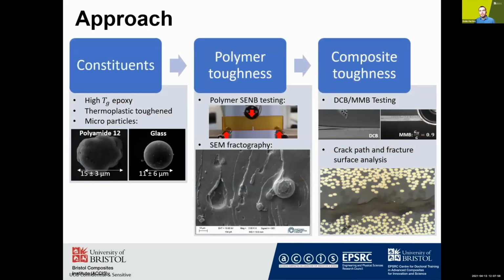And the approach I took was to start with the base constituents, formulating a high-performance epoxy matrix and sourcing two particles of similar dimensions, one hard and made of glass, and one soft made of polyamide 12. Next, I investigated the toughening mechanisms present in the neat resin and how these differed between the two particles. And finally, I manufactured prepreg and particle-filled resin films for testing in mode 1 and mixed mode.